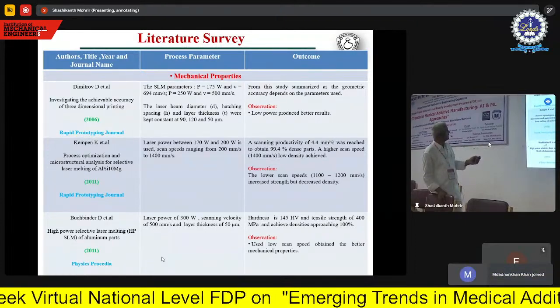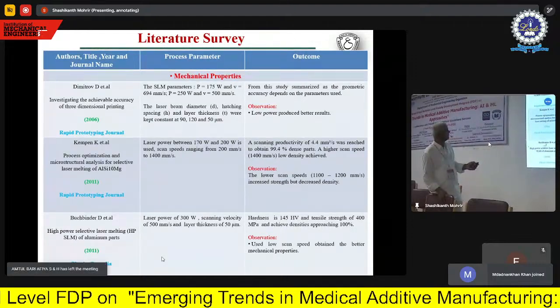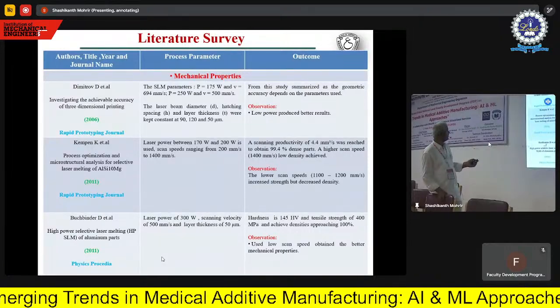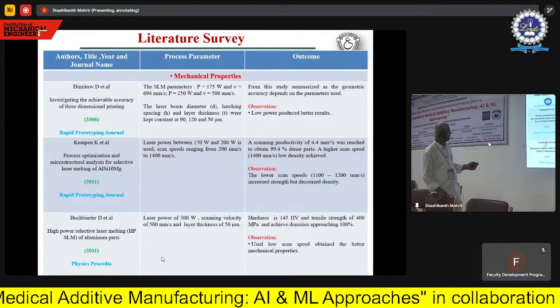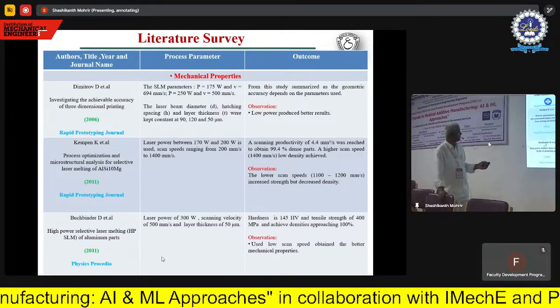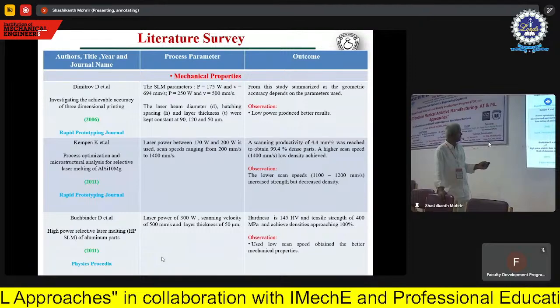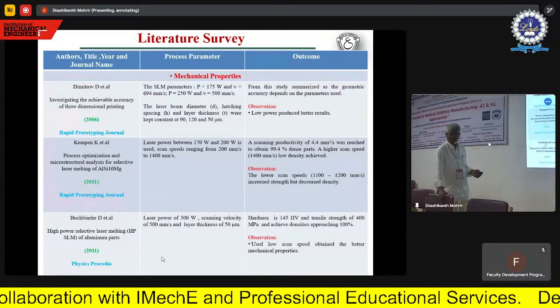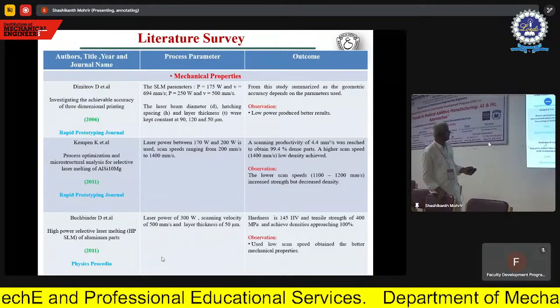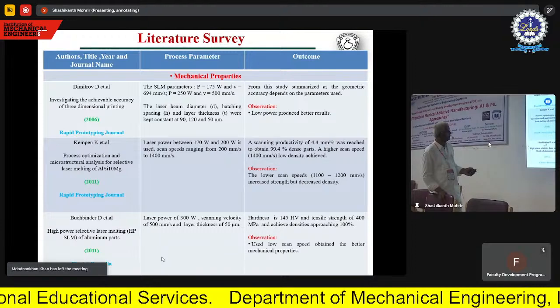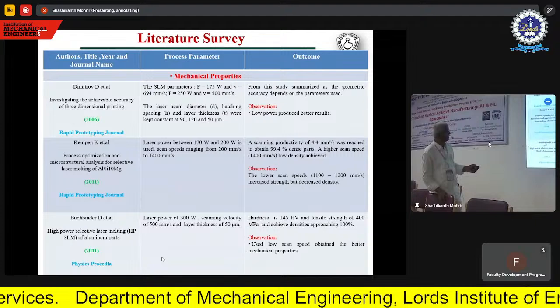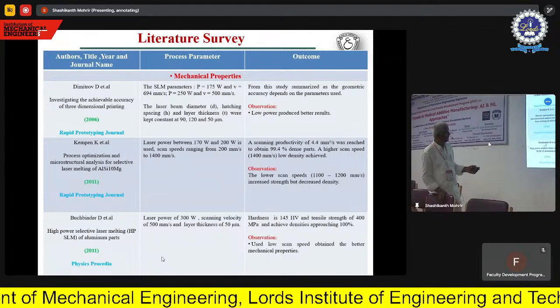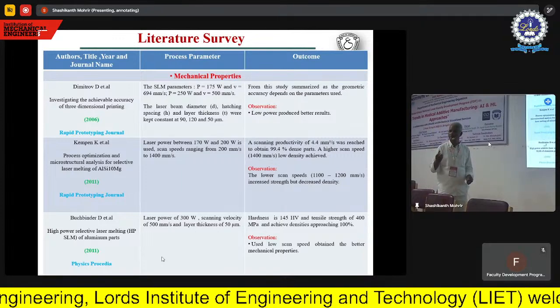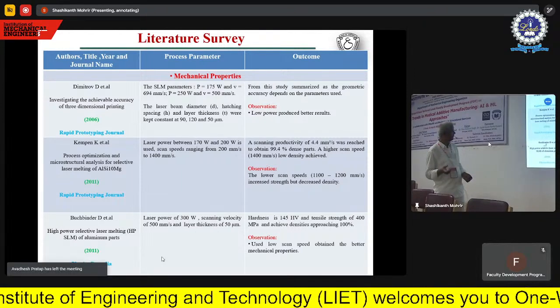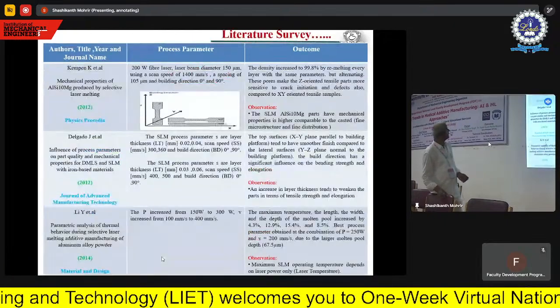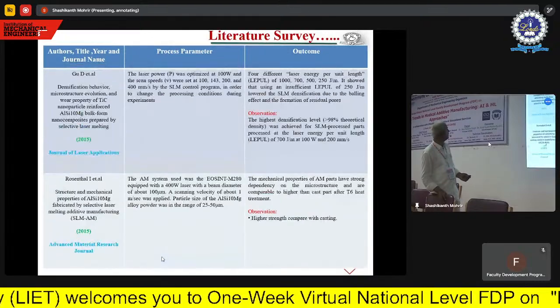Actually, you write page number also. And this is the parameter setting. And this is the observation. And here also, this is Rapid Prototyping, Kempen K. et al. Process optimization, microstructure analysis of SLM of AlSi10Mg. So 170 watts to 200 watts is used. Scan speeds 200 to 1400 mm per second. So observation is lower scan speeds, 1100 to 1200 mm per second, increase strength but decreased density. That's the observation. So like this, you need to conduct a systematic study to arrive at optimal parameters. Okay. So these are mechanical parameters, all from different journals.